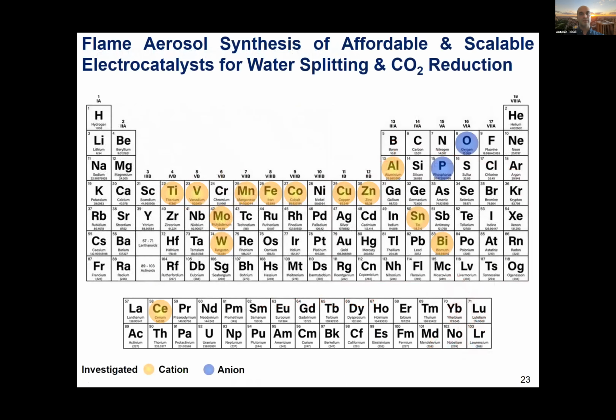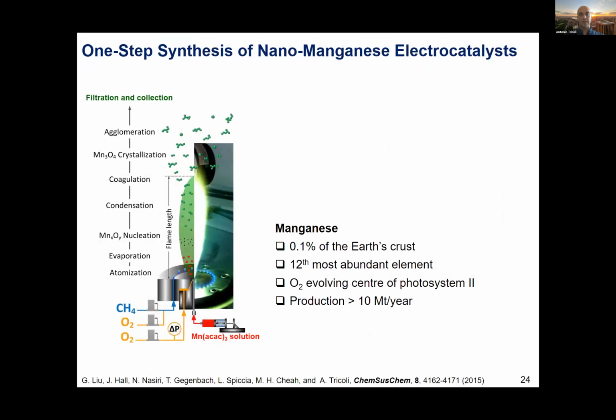In the past years, we have actually investigated the use of flame aerosol synthesis of electrocatalysts with a wide variety of cations and anions, mostly oxygen and phosphor. But in terms of cations, we went into various transition metals, such as manganese and so on. And we have been trying to understand if by combining these metals, by creating more complex perovskite-type structures or ternary metal oxides, we can actually improve and optimize the catalytic activity for water splitting of this material and other processes. I'm going to show you a couple of them.